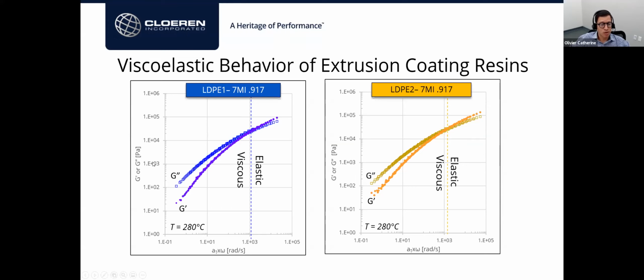So what we are representing here are the different components of the complex modulus. The G double prime, which is the more viscous component of the modulus, and the G prime, which is the elastic component of the modulus.